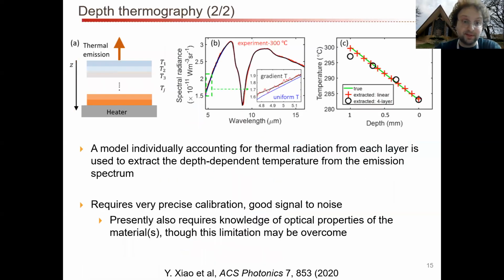Here's an example of this. What we did is we took a heater stage, and on top of it, we put a test sample, which for us was, again, just a fused silica window. It's actually a thick fused silica window that was about 1 millimeter thick. And we measured the spectral radiance versus wavelength using our technique. We were very, very careful. And if you take a look, you find some interesting things that you might not expect to see.